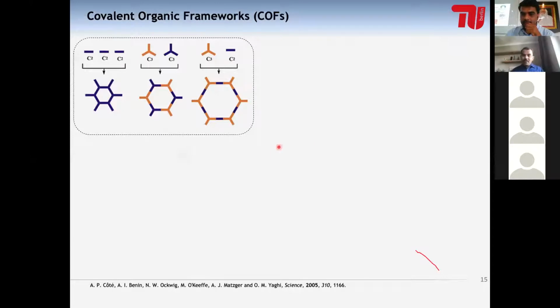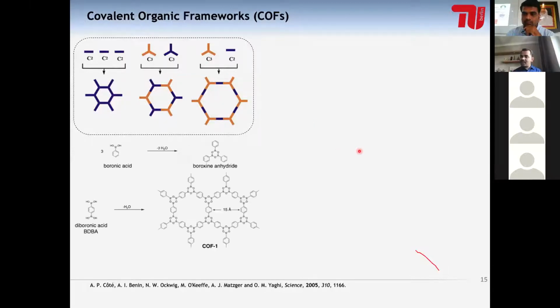Okay. So in these cases, when two C3 symmetric linkers, C3 plus C3 linkers, and C2 plus C2 linkers can be assembled together, they form honeycomb kind of structures. So how can we do that? Now we come back to the organic synthetic conditions, where all of us know the boronate boroxine anhydride formation reaction, where three boronic acids can come together forming such a kind of monomer, and there is release of three water molecules which can drive this reaction back and forth, forming perfectly crystalline materials as well as materials with high porosity.